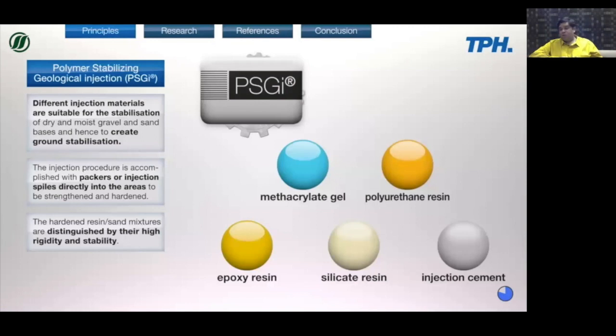Polyurethane resins we have been using for a very, very long time. We have both foaming polyurethanes, which can be used as fill materials. Today you have structural or very rigid polyurethanes, which are also very high in strength, almost easily more than about 70 newton per mm square. So we can reach those kinds of strengths with polyurethane resin as well. And the other ones are much more for ductile filling, which means that they can penetrate well through your strata, but at the same time have enough flexibility to take care of some movements.